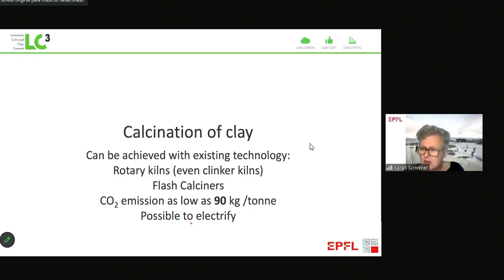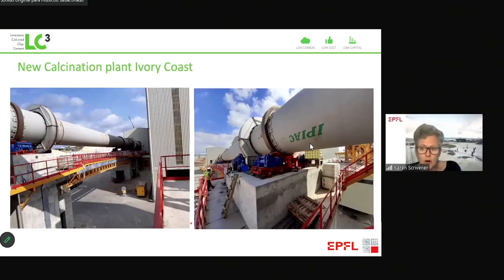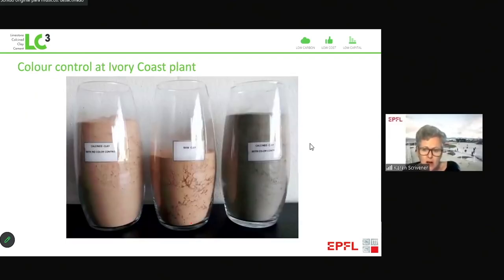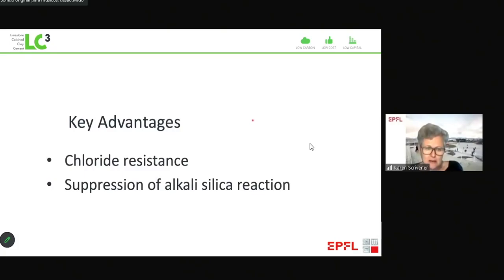And I think in the medium term, we can even see that it will be possible to electrify these kinds of calciners. So this is an example of one of the first plants which was built in the Ivory Coast. I'm sure you'll hear a lot more about this from the manufacturers today. But what was really nice in this plant is that they could really demonstrate that it's possible to control the color. Because when we first started talking about calcined clays, many people were saying, well, we don't want this red color. People don't like red cements. Well, in some applications, red cements could be quite good, but never mind. If you want gray cement, you can have gray cement quite easily.